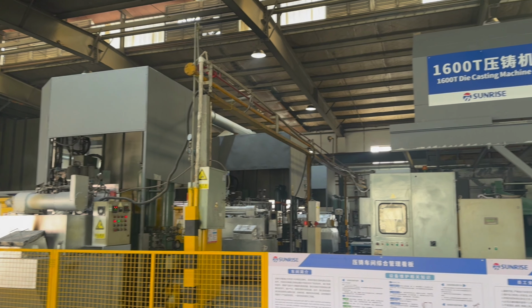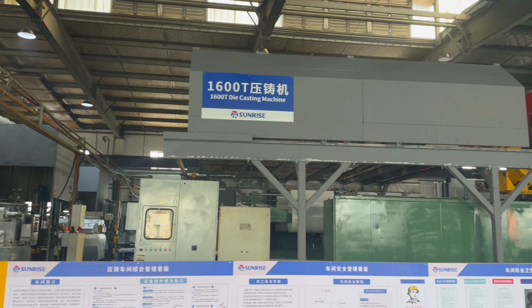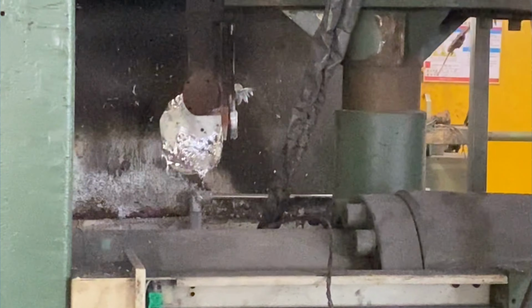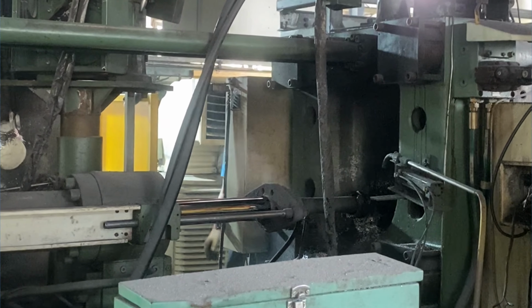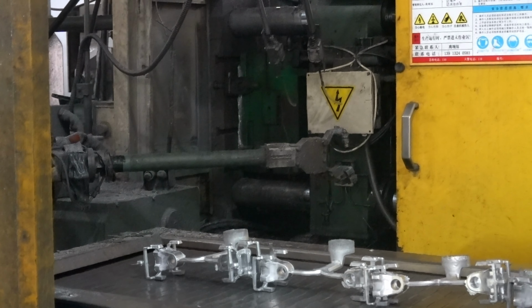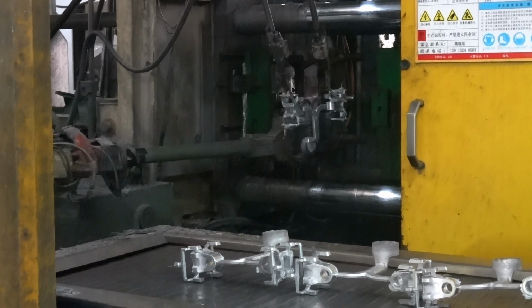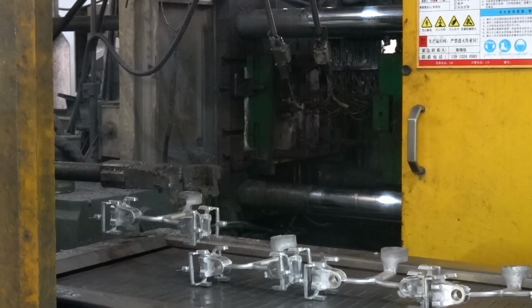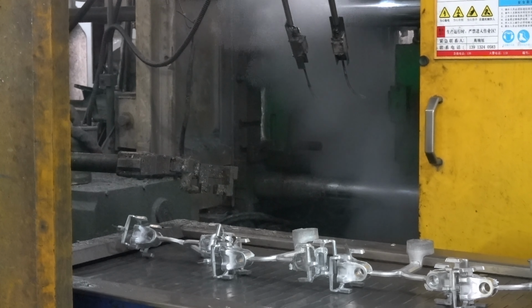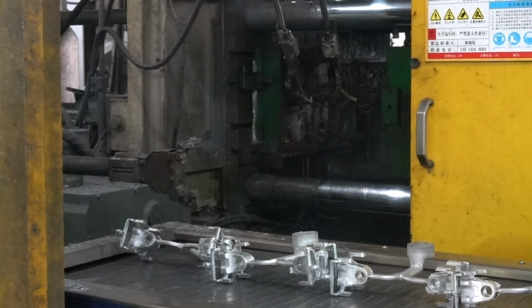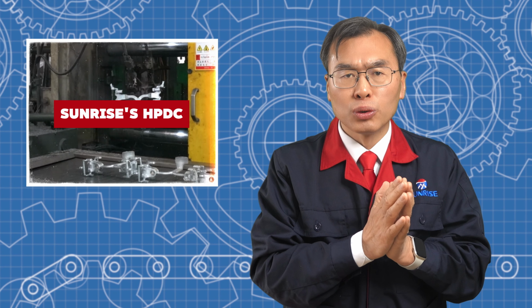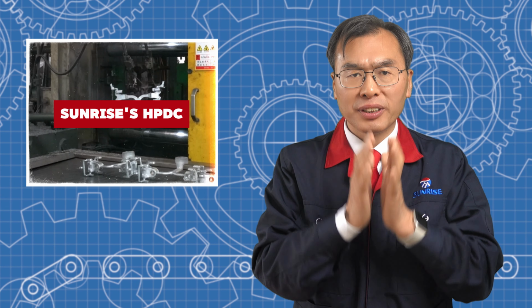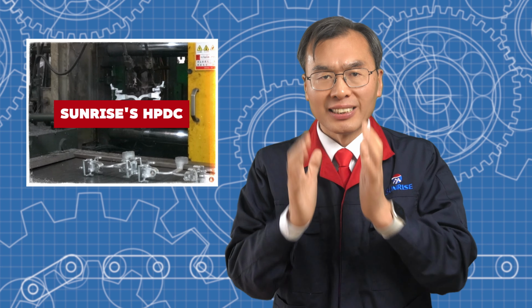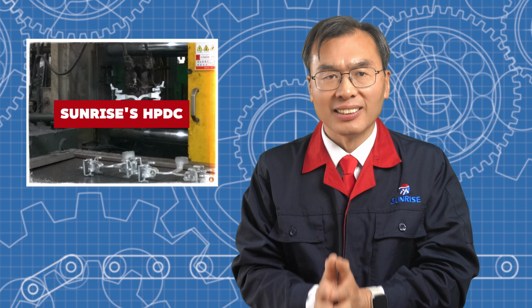Sunrise Metal uses advanced high-pressure die casting technology to make high-precision aluminum parts. Melted aluminum is moved by a robotic arm into the injection chamber. High pressure pushes the metal into a steel mold, where it cools in seconds. Once solid, an eject system removes the casting. The mold is then sprayed with release agent to prepare for the next cycle. The part goes through cooling and post-processing to ensure quality. This controlled process ensures accuracy, consistency, and efficiency.